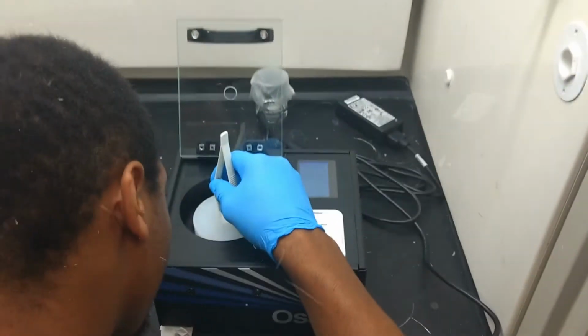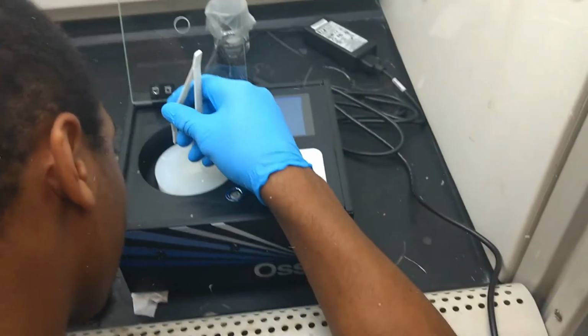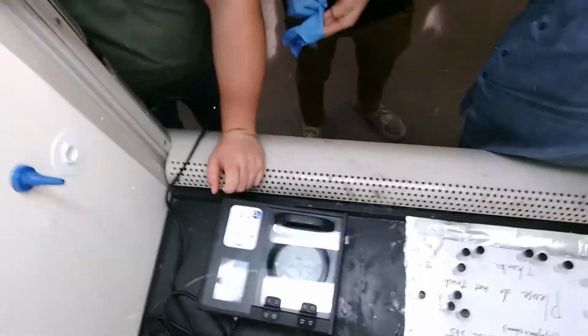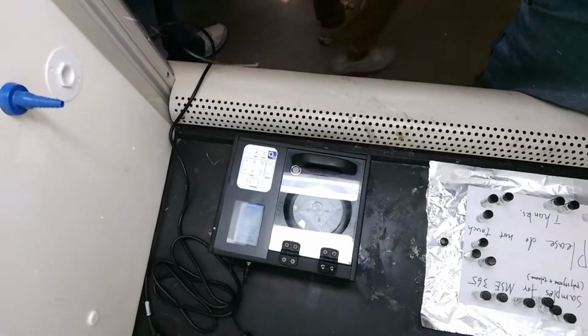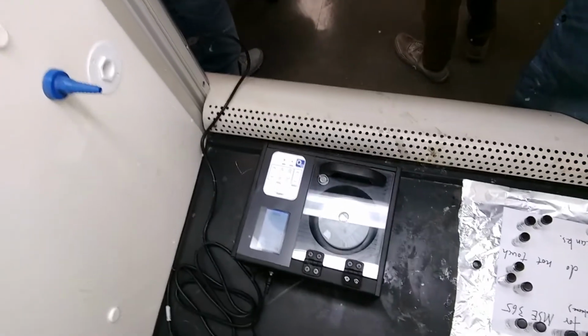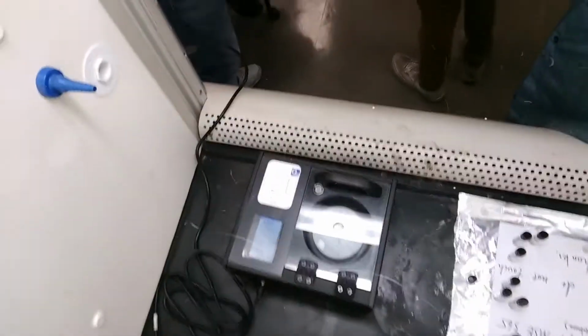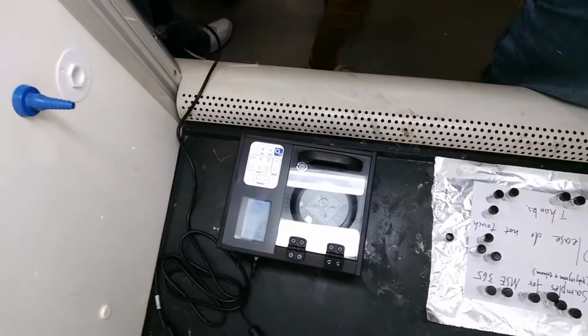To deposit the thin film, a controlled amount is dropped onto the spinning substrate during the deposition stage. After the other solutions have been deposited on their substrates, the samples are placed into a desiccator to dry.